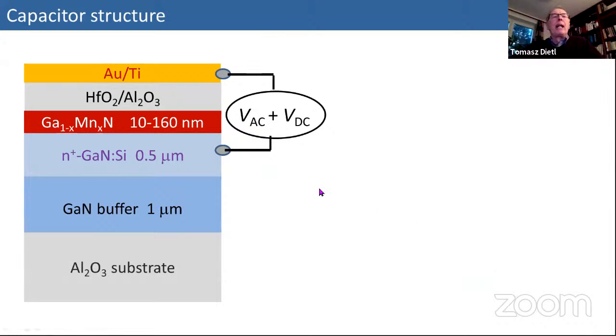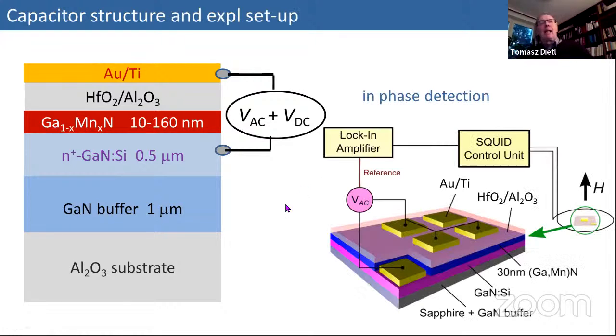And we put this gallium manganese nitride in a capacitor structure. We have N-type gallium nitride with silicon as one plate of the capacitor. We have gold titanium as the other plate. And we look at how the gallium manganese nitride magnetism changes as a function of applied voltage, so as a function of electric field. Technically, we modulate the electric field with some frequency and measure magnetization in phase with the applied electric field. We can add some additional DC voltage, and then we measure, in a sense, the derivative of this dependence on the electric field.